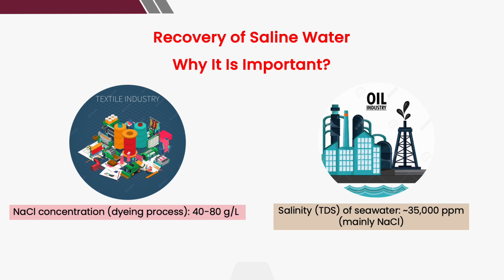And when the dyeing process is completed, the industry discharges a lot of wastewater containing NaCl and the dye. So in this case, we are thinking about, can we recover the saline water from this dyeing process by rejecting only the dye while allowing the NaCl to pass through the membrane. And when we are able to recover the saline water, this saline water can be reused again for the dyeing process, and you don't have to discharge it and use again the NaCl.